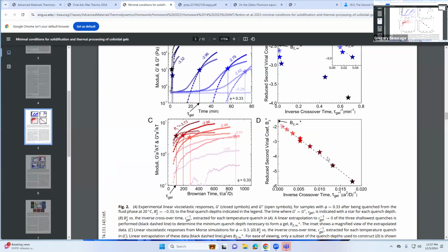And then he says that at short times it gels faster. At long times it'll gel at a more equilibrium point. So the longest time, that's equilibrium gelation, which there's no other way to get. You can't measure at infinite time. So he plots versus 1 over time, and he gets a linear dependence, and he finds his B star as the intercept of that. It's a little complicated. It's a way to get B star. In simulations, you don't change the time.